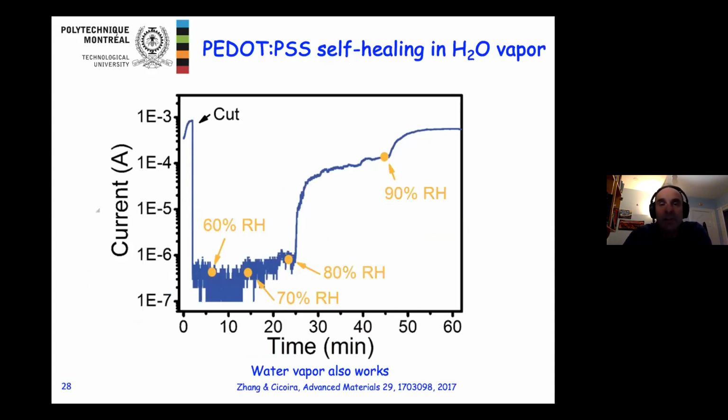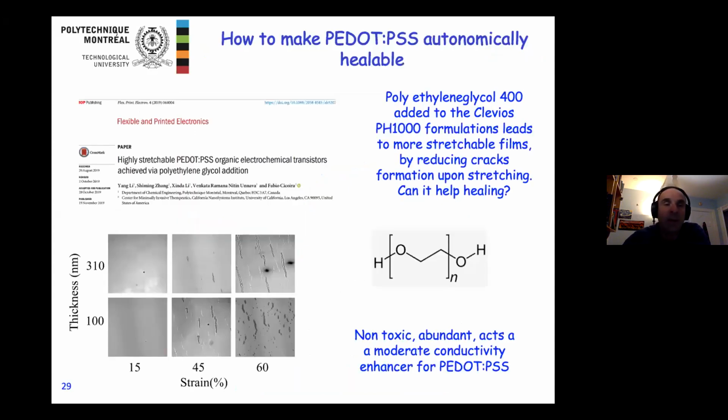What is also interesting is to see how this material reacts to a vapor environment. We did the experiment in a humidity chamber where we changed the humidity, and what we saw is that after the cut, when we reach 80% relative humidity, we can also see the healing effect in the presence of water vapor.